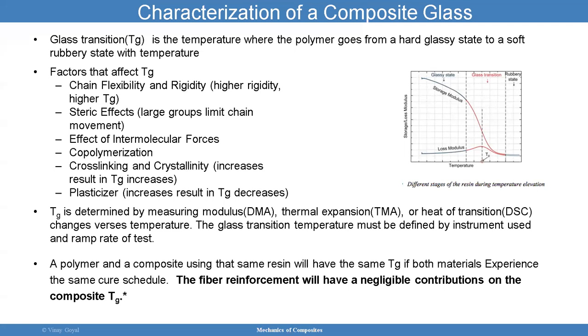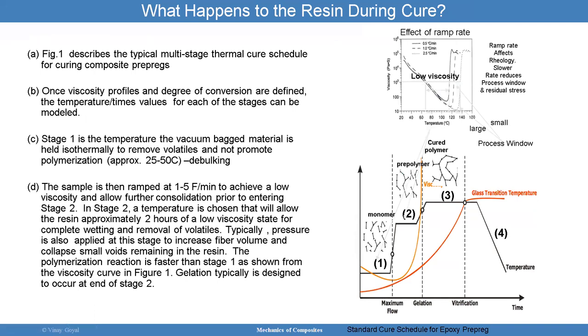The fibers have very negligible contributions to TG, but again, the TG is basically forensic science. It's telling us the degree of cure, and if there was a problem, say there was a problem with the oven or something happened, I can check the TG. And if the TG looks different from what I qualified the material for, then I know there's something going on that I had to go and examine, right? So that's what we're getting at here.